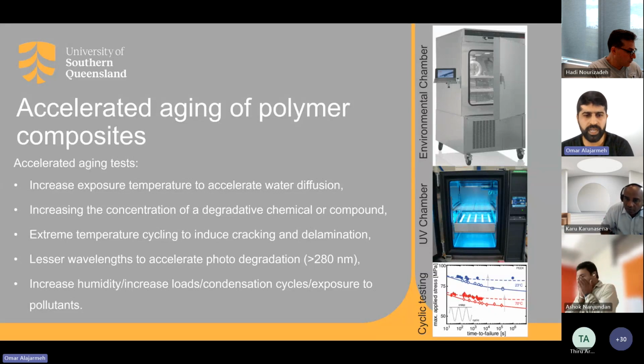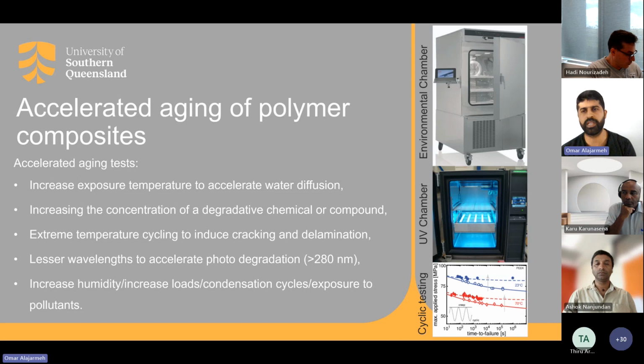We have wavelength to accelerate photodegradation, which is more about UV. So you can control the UV energy using some lamps and give different energy waves for that polymer to react or to accelerate the degradation. Increase the humidity, increase loads, and condensation cycles, which is more about mechanical testing. So you can change the creep load, the level of load. You can change in fatigue the stress ratio. You can change the upper bound and lower bound of fatigue testing.